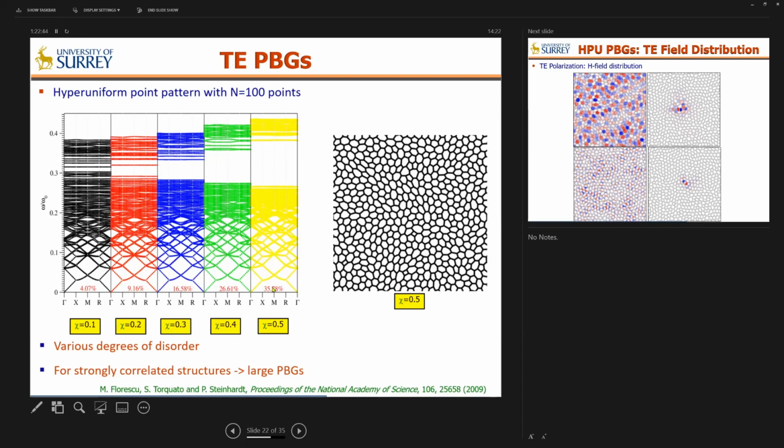Throughout the evolution, we maintain the position of the band gap at band number equal to the total number of cells present in the system, which means that the band gap origin can be traced to the individual scatterers in our system.